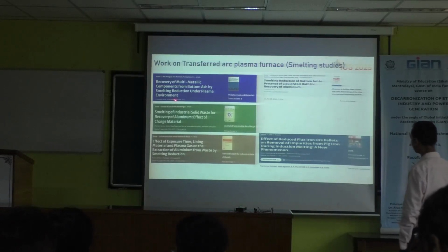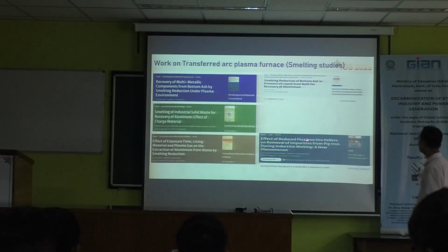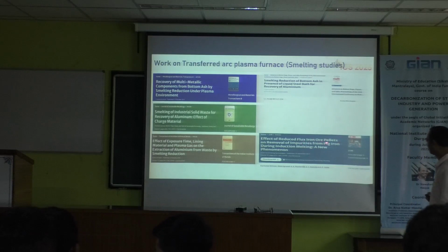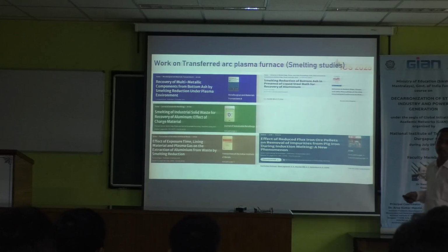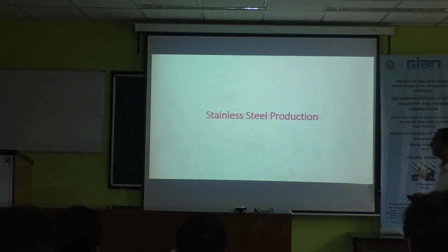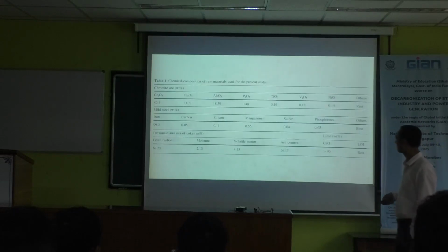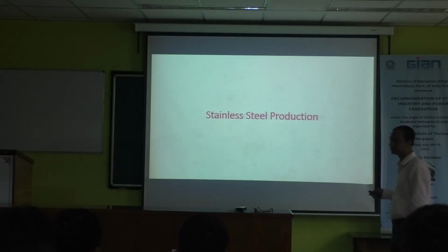From this study, we have published papers, one of which I discussed, on pig iron slag pellets, optimum slag pellets for the removal of impurities from the pig iron. We have an induction melting furnace, and we have compared with the lime, conventional lime also. Then another thing we have done in this furnace is stainless steel production.